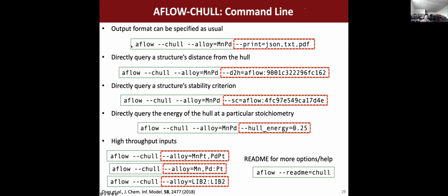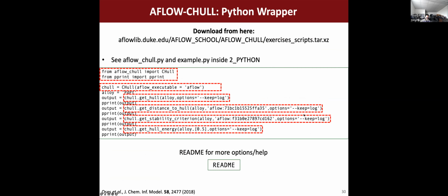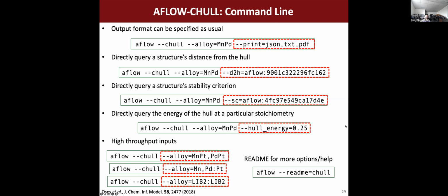So I'm just going to list the commands here. We're not going to have the opportunity to try them, but you can actually query the convex hull data through the terminal. So you can get the PDF as I showed you from the web. You can get a JSON response, which is nice for integrating with Python, and a text response if you want to read things more in a tabular sense. You can get the distance to the hull for a particular entry. Okay, so if you know its AUID, you can retrieve back exactly what the distance to the hull is. You can get its stability criterion. You can query the energy at a particular stoichiometry by providing the composition.